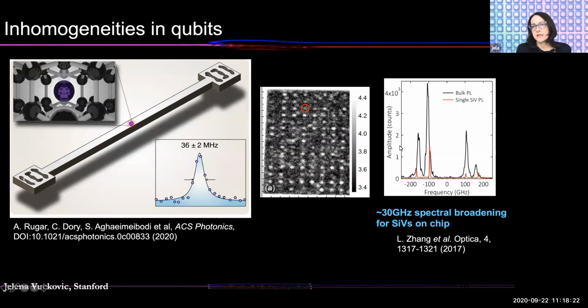But the other problem that we have to face and deal with is what you see on the right, and that's inhomogeneous broadening. Normally, if you have a single emitter, you would see the spectrum. This is in this case for silicon vacancy, as shown with the red curve. But when you look at the ensemble of these color centers on the same chip, you will actually have transitions that vary by about 30 gigahertz. And this inhomogeneous broadening, so line width is pretty much preserved, but transitions vary from color center to color center, are results of imperfections in the environment and the crystalline structure.